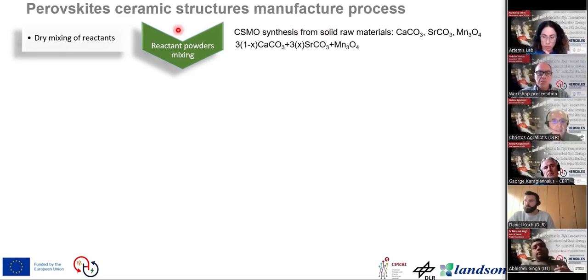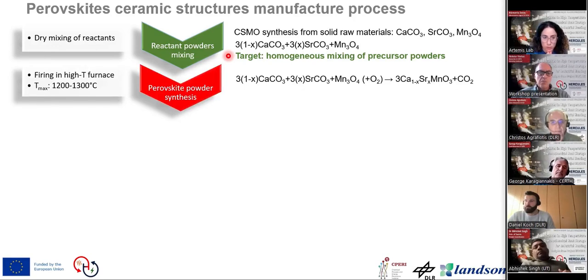So first we do the powder mixing, because we have first to synthesize the perovskite phase, as we saw before, calcium manganite. Then if we click, after the mixing we have to sinter. As I said, the target is to have a homogeneous mixing. Then we sinter this mixture of the precursor raw materials at high temperatures so that this solid state reaction takes place that you see there. And if everything goes well, a single phase perovskite is formed according to the stoichiometry that we selected.